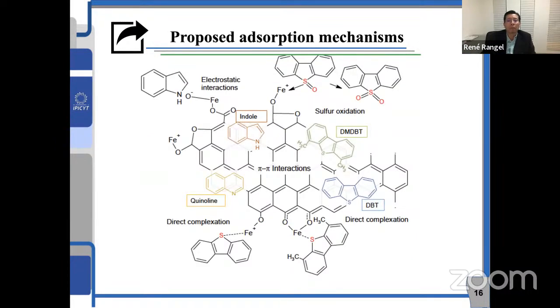So what have we done? Well, we have designed different carbon materials to remove these contaminants. As you can see in this schematic, these molecules can be removed on the graphene layers by pi-pi interactions. But also we can increase the removal of these compounds when we include in the activated carbons metal oxides like iron. Here, this iron oxide can give you negative and positive charge. And so these charges can interact directly with these sulfur and nitrogen molecules. So that scheme will explain how we can remove these contaminants.